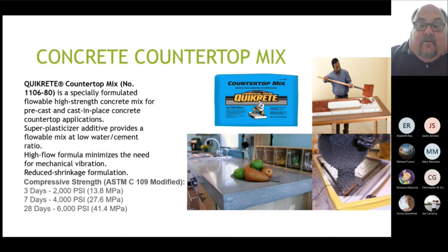What makes this different than a regular concrete mix is it's really specially formulated. It's got plasticizers in it that make it flowable without adding excess water, which was a big pitfall of people doing concrete countertops because they were trying to get it around molds. They added too much water so they could work it, and there's a lot of shrinkage cracks, and a lot of issues with the spalling on the top. So with this, your lower water content and the plasticizer's workability increase the strength and the success rate of the product. You're looking at 6,000 psi.